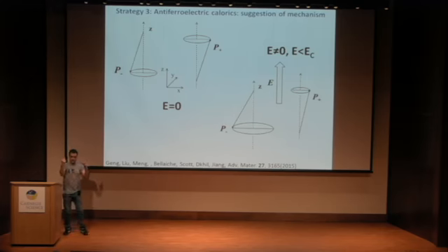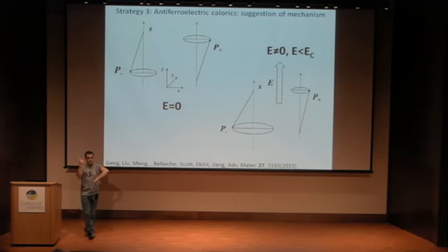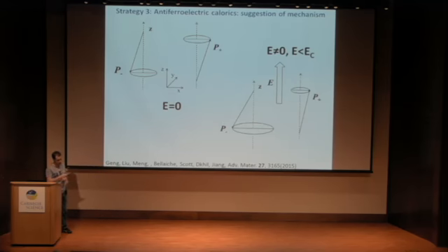We have an anti-ferroelectric system, but it's not fixed. The dipoles are not fixed like this. There are always some oscillation around this axis. And then when we apply the electric field, this one will follow the electric field, while this one wanted to rotate. And because of the rotation of this dipole, or the amplitude associated, or the movement, or the dynamic, or the disorder associated to this guy,